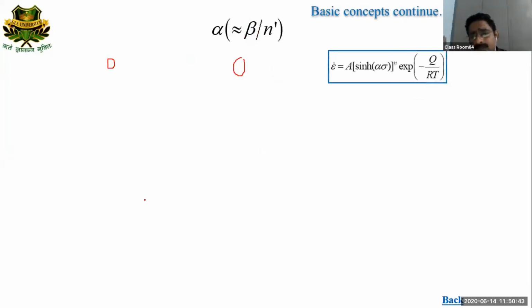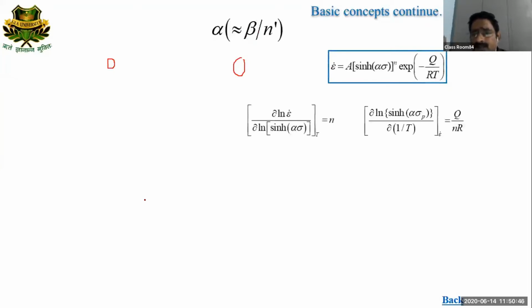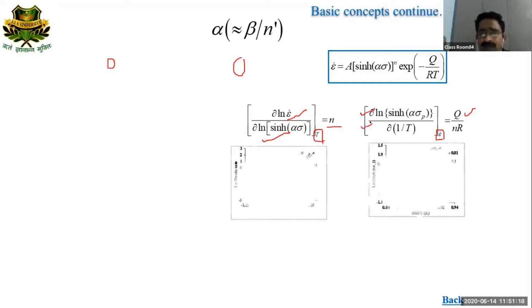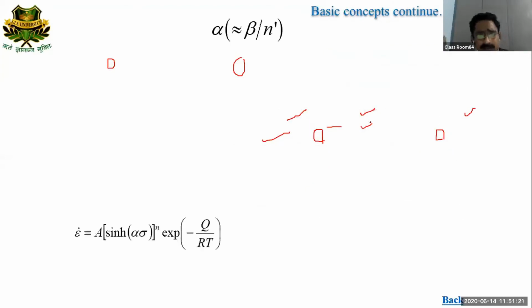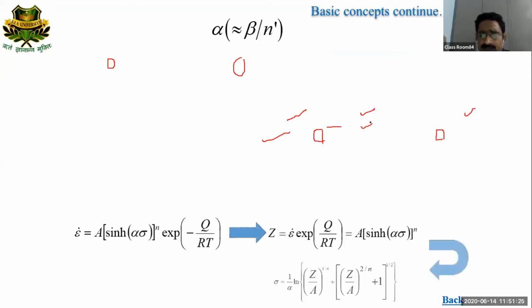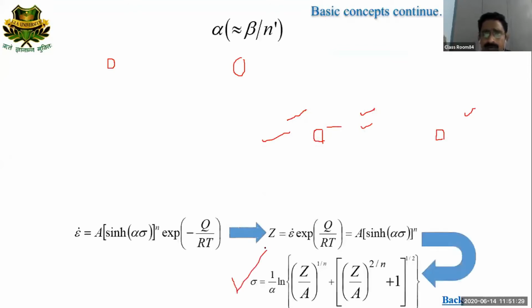With this sine hyperbolic constitutive equation, we can generate the value of n as well as the value of Q. When we plot our data in terms of ln strain rate versus ln sinh alpha sigma, then we can get the value of n. But it is to be noted that under this condition the temperature must be constant. In the next case, when you are calculating the value of Q and nR, the strain rate must be constant and you have to plot your data in this particular form. With this we can have the values of all the parameters, and by putting them in our equation, we can generate our standard equation to recalculate or generate any data which was not performed during the simulation.